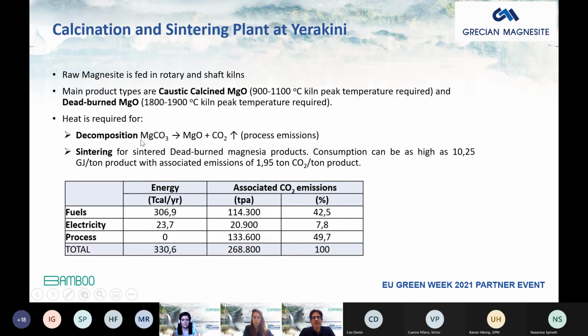Now the heat goes, of course, for the decomposition of magnesium carbonate, where you have the emission of CO2, and these are the process emissions, and for the sintering of the magnesium oxide to form dead burnt magnesia. In that case, this can be highly thermally demanding. For example, for a certain dead burnt magnesia product, the consumption can be as high as 10.3 gigajoules per ton of product, with associated total emissions, both fuel and process, of almost 2 tons of CO2 per ton of product.